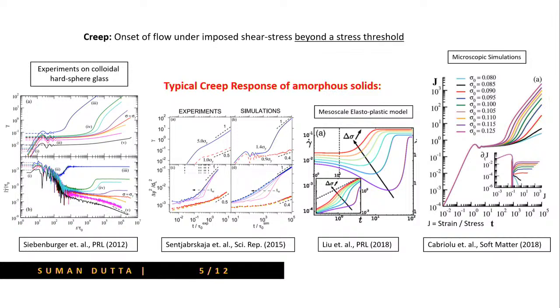For glassy systems, things are very, very slow, and glassy materials can have different characteristics depending on their preparation. In the experiments, people have realized that different kinds of glass have different responses. For glassy yield stress materials, which is also valid for other classes of yield stress materials, things flow beyond a particular stress threshold. In the creep curves, one can see three different regimes: the primary regime, then the secondary regime, and a third regime when it flows. Otherwise, it gets arrested at very long times.